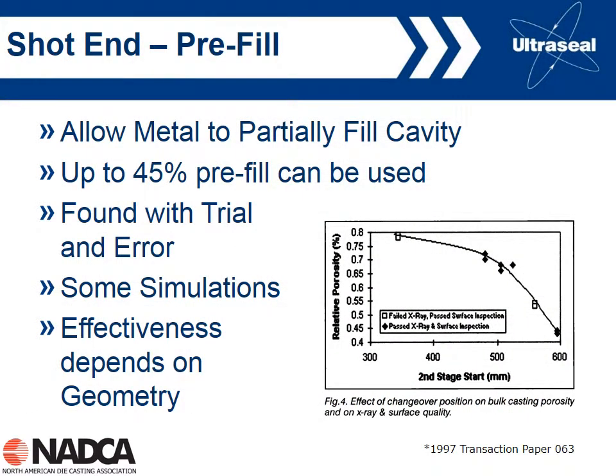Let's talk a little bit about pre-fill. Pre-fill is quite commonly used to help control porosity in die castings. Again, NADCA did a survey and found that around 50% or so of die casters have used pre-fill from time to time in filling their castings. Traditionally we would start the fast velocity either when the metal's at the gate or just before the gate. But with pre-fill, we basically continue the slow shot velocity into the cavity, and it's certainly been shown that it can reduce porosity in die castings.